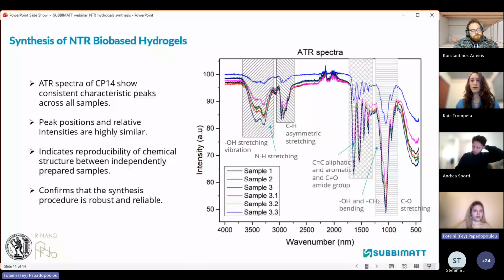So we did ATR spectra in different batches of our experiment. And these ATR spectra, as you see here, are from 3 different samples, and from one sample we did 3 different areas. In order to do that, we freeze-dried the hydrogel from 3 different batches in order to see the replicability of our process. The peak positions and the relative intensities are similar, as you can observe, and this indicates the reproducibility of the chemical structure between the independently prepared samples. So with this, we can confirm that our synthesis procedure is robust and reliable.